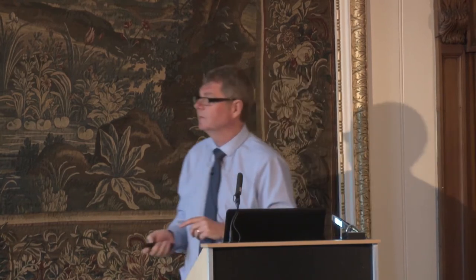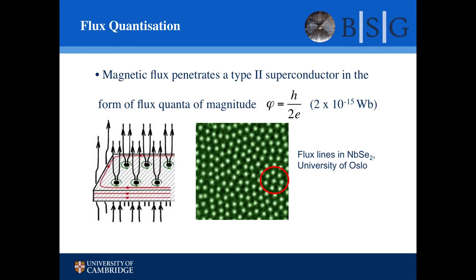However, in a superconductor, lines of flux do exist. It's extraordinary. So here we have a superconductor actually produced in Oslo, and as soon as flux enters a superconductor, it becomes quantized. It actually forms thin filaments of magnetic flux. And you can see them schematically here threading through the material. And you can actually see these lines of flux. You can decorate your sample with something that's magnetic and offers contrast under some microscopy. And that's exactly what's happened here.